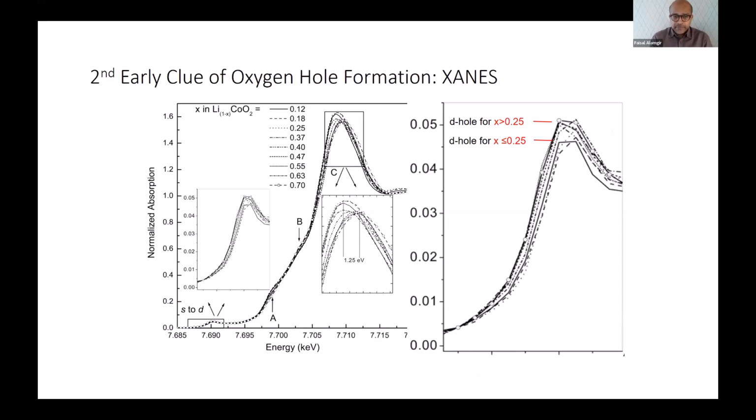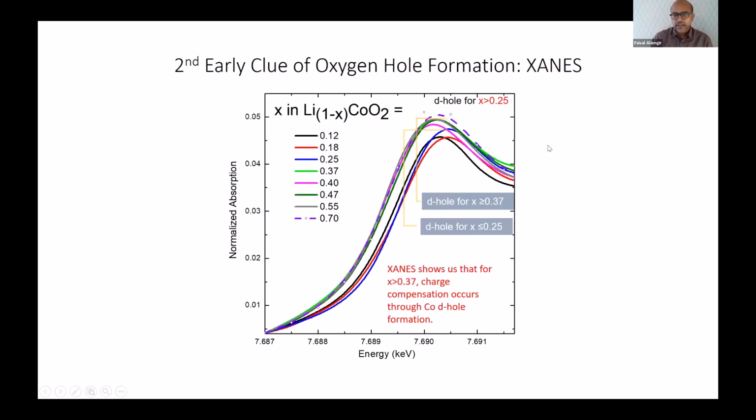That transition where you see the splitting up until 25% de-lithiation and then recombination seems to correspond with the quadrupolar transition, the pre-edge peak here. When we zoom in, and it'll be clearer when we look at it here, you can see that there is one transition happening pre-25% and another beyond 25% that is fairly clear.